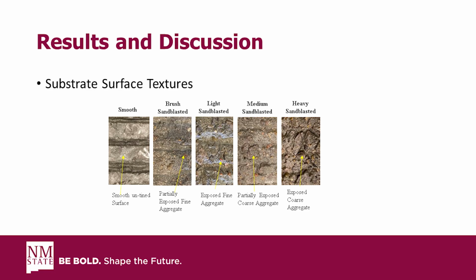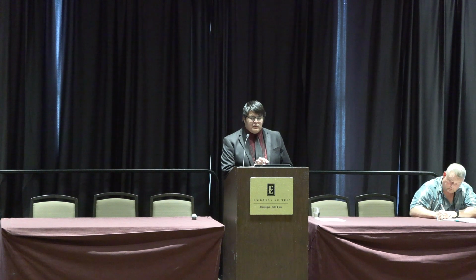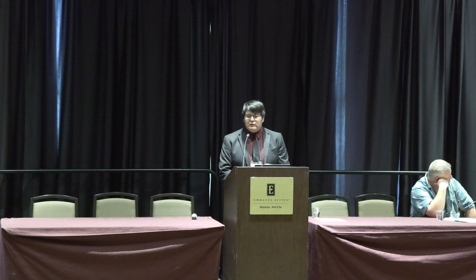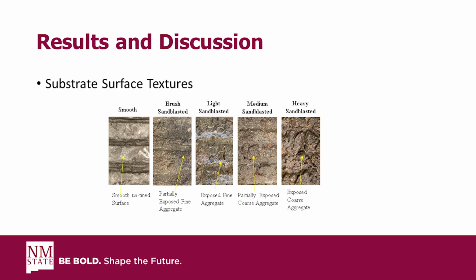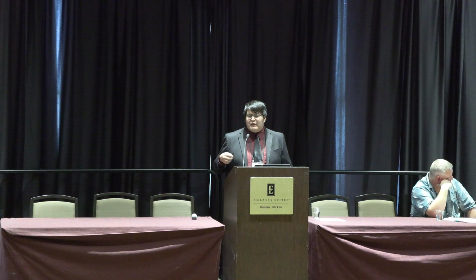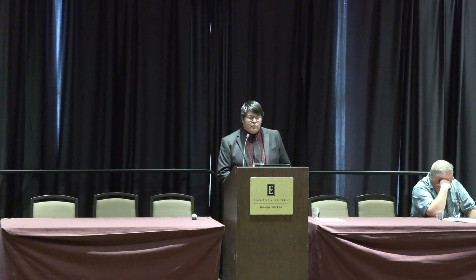And one thing you need to note is that the smooth case is where we didn't remove any of that surface space. And so the smooth case is at saturated conditions, okay? So that means it's the ideal case. We have a saturated surface, we're not dry. However, by not removing any of that surface space and exposing any aggregates, we don't develop good bond. We do develop bond, but it's less than 150 psi on average. And by exposing more aggregate, we get more bond strength.